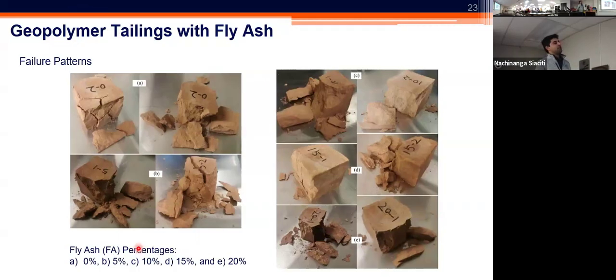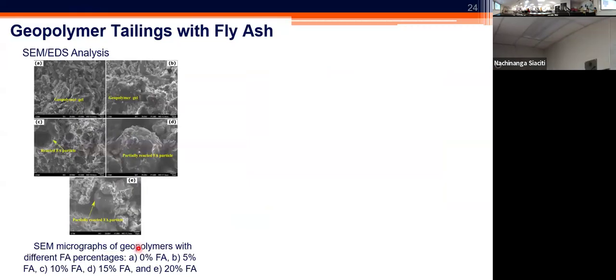And then we looked into the process as to why the additional presence of the fly ash, let's say the 20%, didn't really make much improvement in the properties. We realized that as we exceed the 15% fly ash, any additional amount of fly ash simply remains inert and intact and untouched, and does not contribute or participate in the geopolymerization reaction. So any amount of unreactive content, even from the fly ash, can be a bad thing, maybe because you are incorporating fly ash as a commercially available type material.